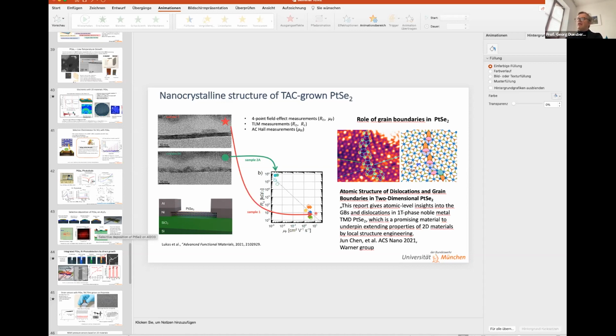For the larger substrates, we actually go to hydrogen sulfide precursor and metal organic, MO, precursor, which is typically done in wafer scale furnaces. But you are talking about an investment of at least $500,000, because you have very toxic precursors and big tools. I don't know if you have the capabilities at ICM2, but the problem again is that nice crystalline monolayers are still very hard to grow with this process. But if he wants to learn more about this microcavity approach, I'm happy to answer details or connect him to my students here, who currently pursue it.